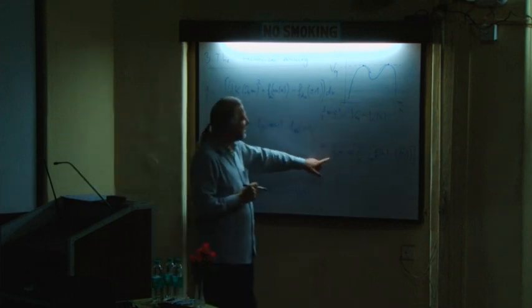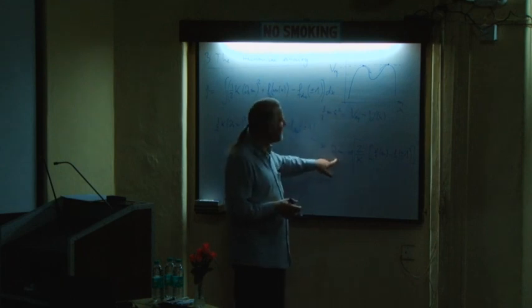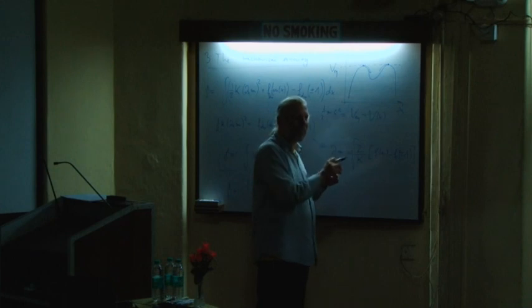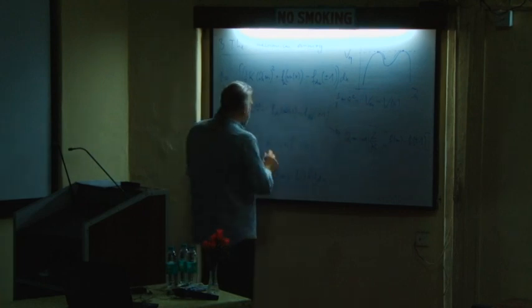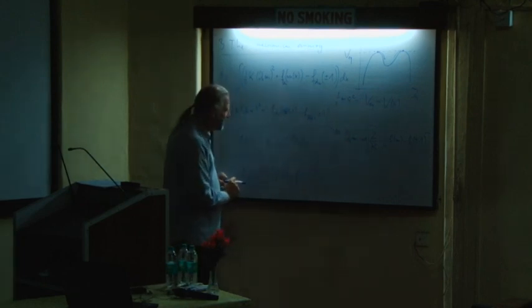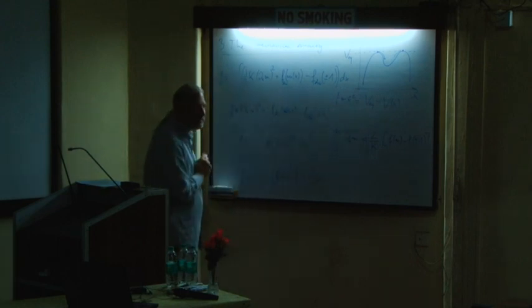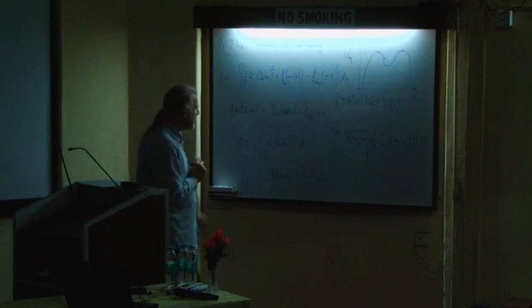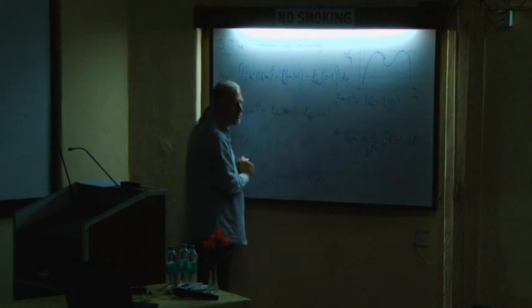So this in some sense tells you the exact relation of the hand-waving argument that I have given you before. The magnitude of the gradient is linked to the height on which you are on the potential well. If you are here, your velocity is highest, and in the analogy, the gradient is highest. Okay? Now, why is this useful? Because now I can transform this integral. The problem why this is difficult to calculate is that my integration is over x. So what I would like to do, this is a function of m, I would like to switch integration variable from x to m.